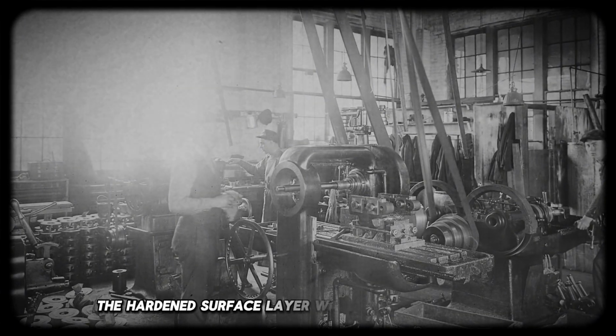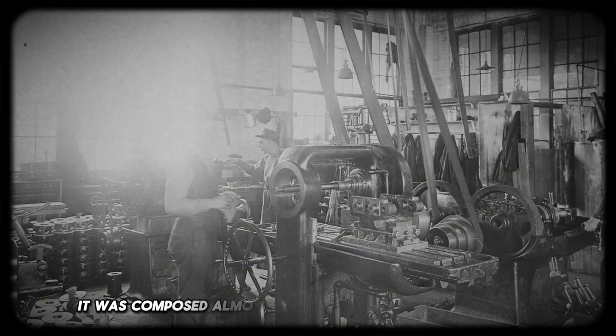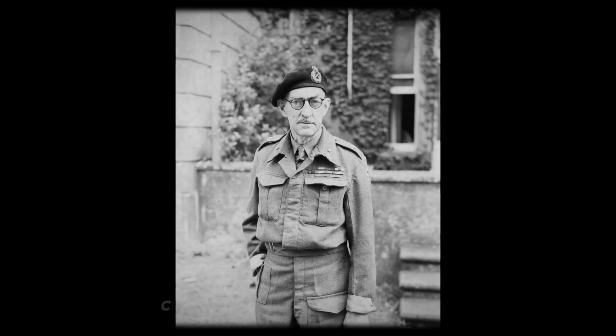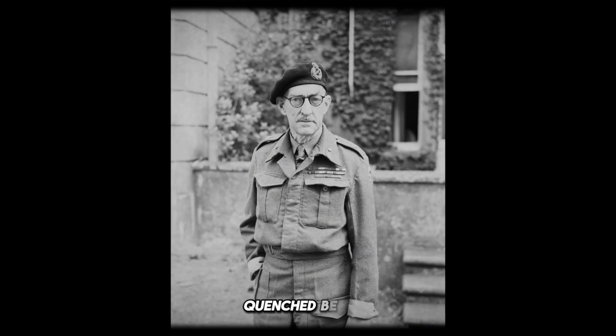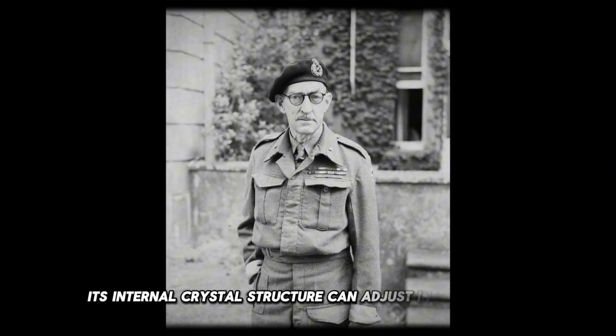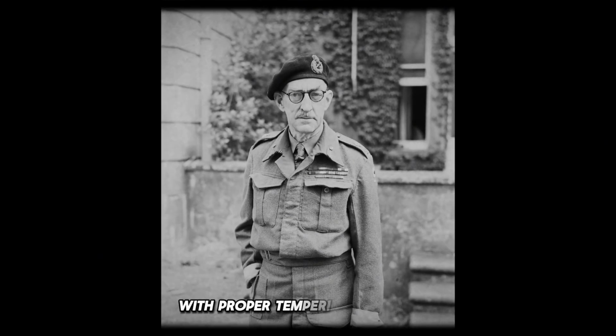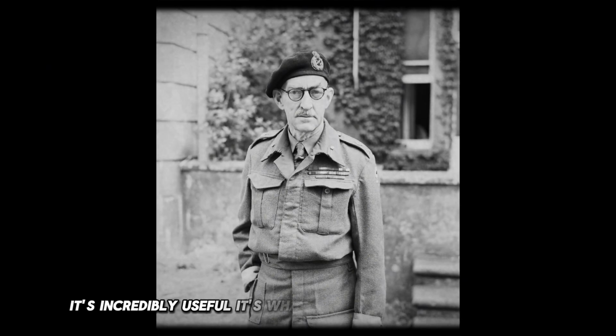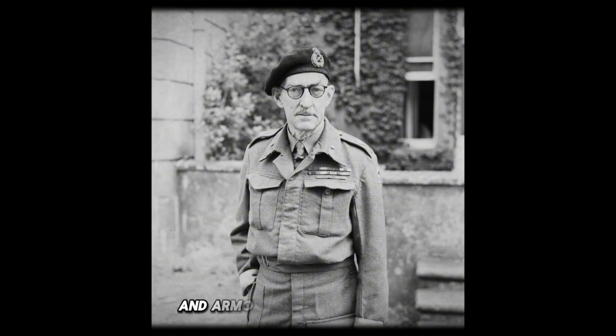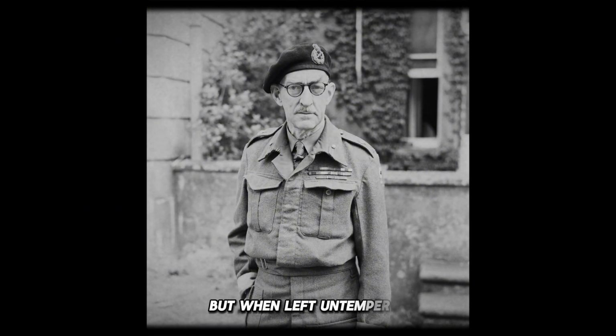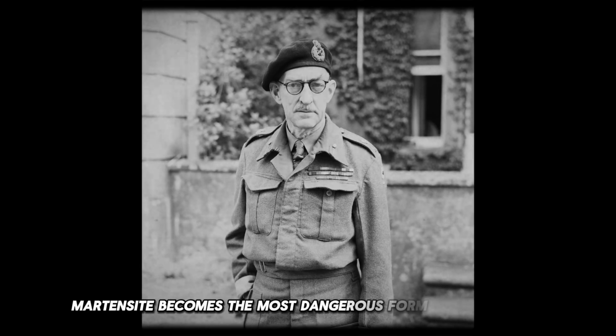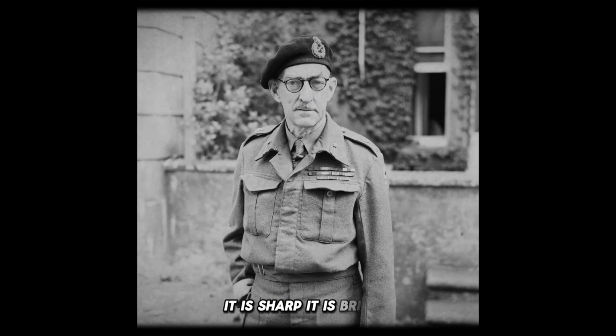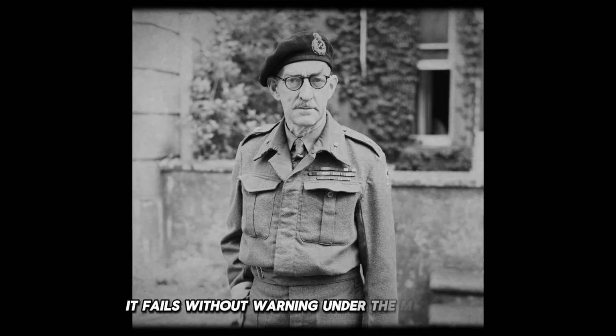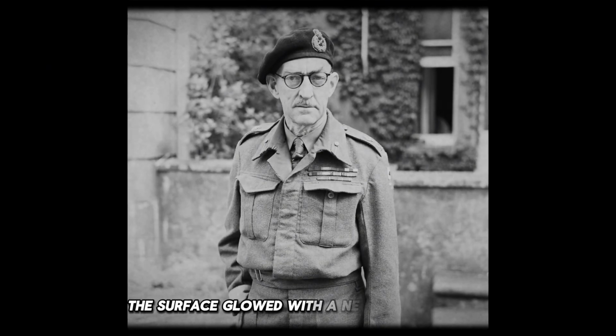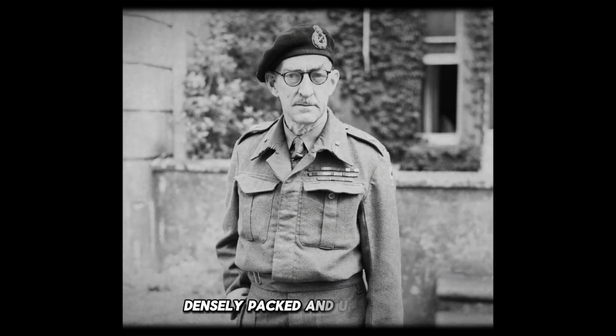The hardened surface layer wasn't just over-deepened. It was composed almost entirely of untempered martensite. Martensite is the hardest phase of steel, created when metal is rapidly cooled, quenched before its internal crystal structure can adjust. In controlled amounts, with proper tempering afterward, it's incredibly useful. It's what gives cutting tools their edge and armor plates their resilience. But when left untempered, martensite becomes the most dangerous form steel can take. It is sharp, it is brittle, it fails without warning. Under the microscope, the surface glowed with a needle-like pattern, densely packed and unforgiving.